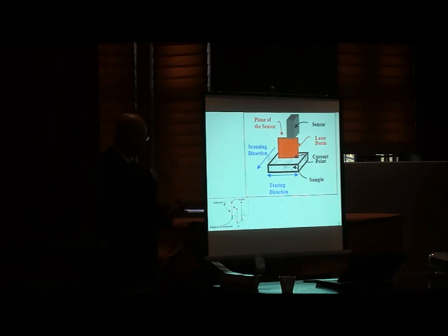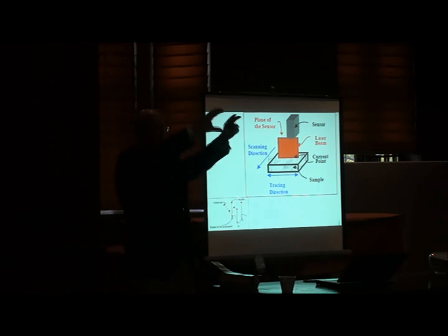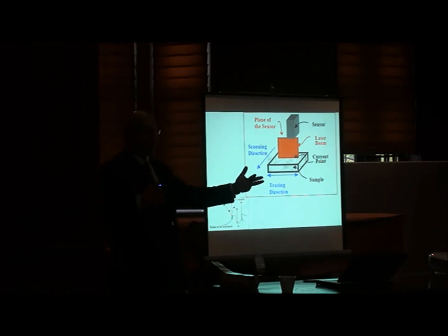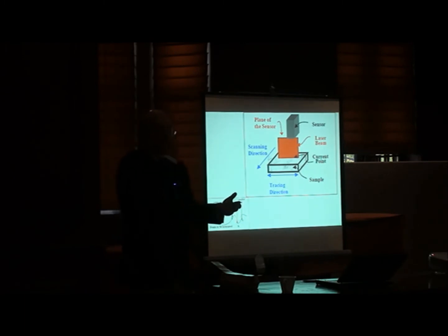We did the analysis both along the tracing direction and the profile direction, and we were able to show that you could clearly group each measurement. If the instrument were not putting any directionality into the measurement, you would have 4 distinct groups of points when you did your comparison. And we had 8 distinct groups of points. So for each set of data, there was a grouping. So I think if you want to know whether this change in directionality is happenstance or from your instrument, you need to do a study like that just to see what the noise floor is on that instrument on that type of surface.